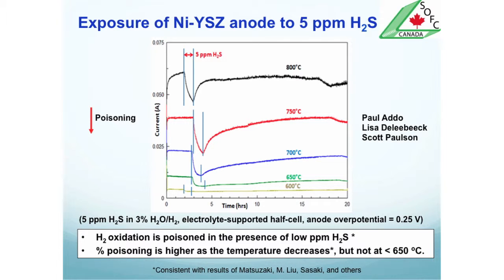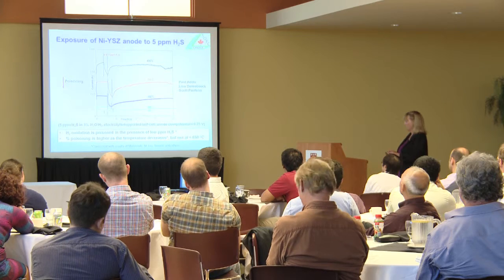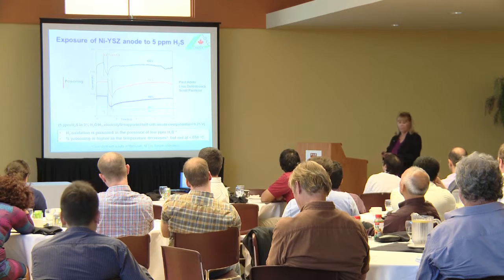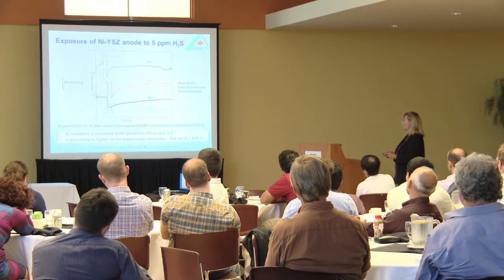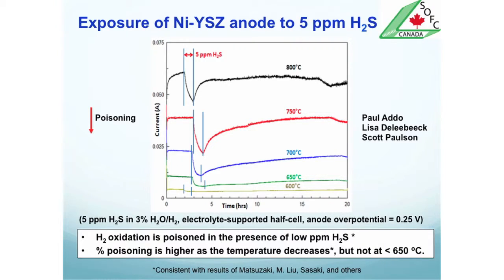And you can see the effect at different temperatures. Immediately you'd be able to see that as you lower the temperature, the currents fall, and that makes sense. SOFCs perform less well at lower temperatures. What you can also see, I'll show you more in the next slide, is that the effect seems to get worse at lower temperatures, and that is what's actually predicted.